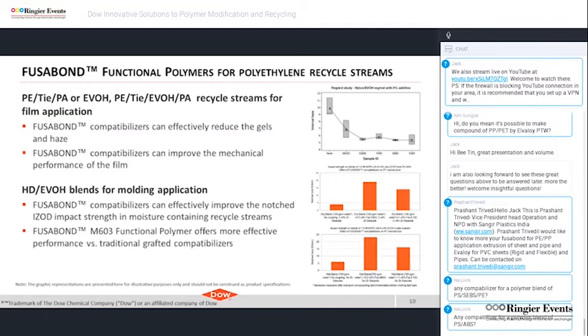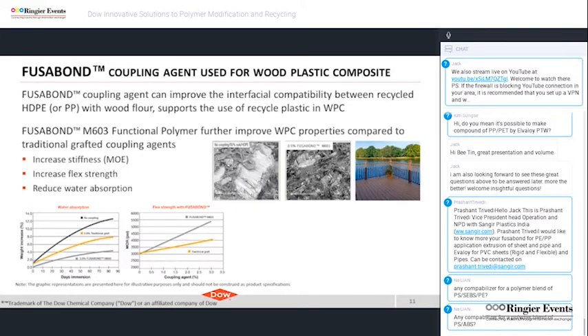At the same time, Fusabond M603 also enables multi-layer films to be used for injection molding application. As shown in the center graph, 0.5 weight% of Fusabond M603 gives better notched Izod impact strength than 1 weight% of traditional grafted compatibilizer in HDPE EVOH blends. It is common for recycled streams to contain some moisture. The bottom graph shows that Fusabond M603 also can effectively improve the notched Izod impact strength in moisture-containing recycled stream versus traditional grafted compatibilizer.